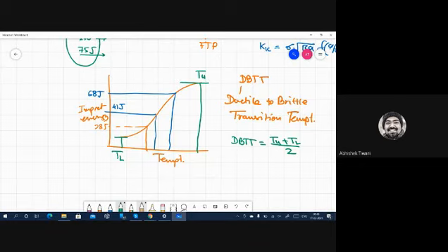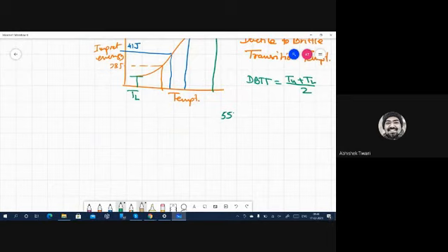For certain materials, you cannot always get 68 joules. One problem was that we were using sub-size samples, right? So 55 cross 10 cross 5. If my 10 cross 10 sample is giving me an energy of 100 joules, then a half-thick sample should be giving me 50 joules. It is not like that. It is just to demonstrate this, but there is a lot going on here, so it will not be half of it, because of microstructural reasons, and also because of the notch.